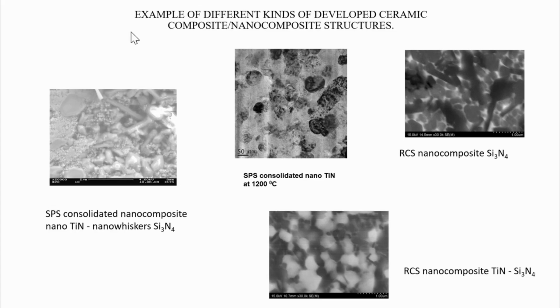Here you can observe some examples of different kinds of developed ceramic composites and nanocomposite structures. This is a single-phase nanocomposite from titanium nitride grains obtained by up-to-date technology of spark plasma sintering. The nanograin ceramic with elongated grains, multifunctional, multiphase nanograined ceramics obtained by rate control sintering, and nanoceramics which combine the nanograins of titanium nitride and nano whiskers of silicon nitride.